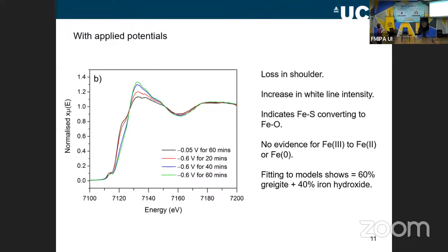So what we did then is we applied some potentials. First of all, the one in black here is when we applied a potential at which no reaction takes place. And the spectrum is the same as for the dry greigite, so it's unchanged. Then we apply a potential of minus 0.6 volts. So that's where that reaction was taking place, where we know the reduction happens. And what you can see is two things. First of all, this shoulder disappears, so it's no longer there. And then secondly, the intensity in this region goes up, so you get an increase in that.